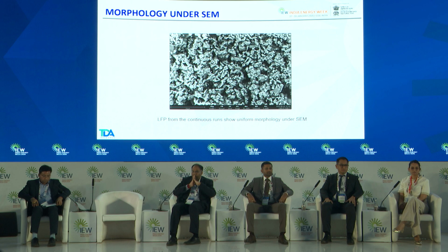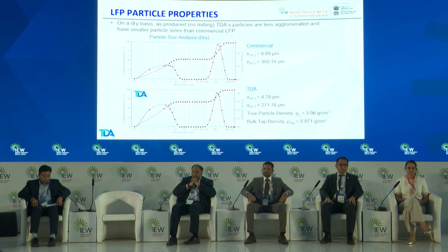This is a scanning electron microscope image of the material. The only point of this image is that it's a uniform material as far as the particles are concerned. So it shows a uniform morphology under the SEM. As I said, our particle sizes are slightly smaller than what you would find with commercial. So the particle size distribution at the 50% and at the 90% cumulative distribution size, as you can see for commercial, it's about 9 micrometer at the 50% and 300 microns at the 90%. We are substantially smaller. We're at about 4.75 or less than 5 microns. And what that translates to is higher performance when you put them into cells and test them.